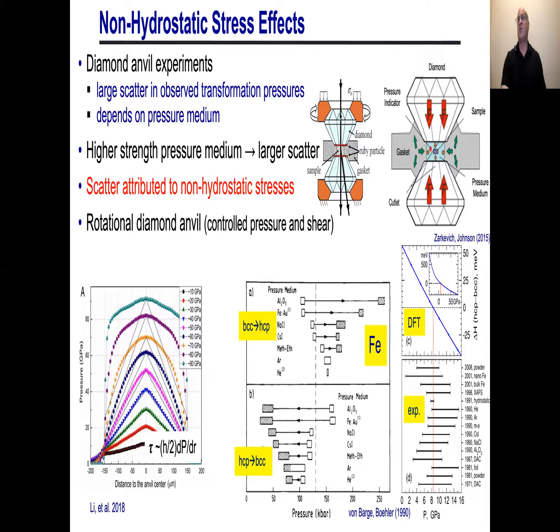People have also created what they call a rotational diamond anvil cell. So that's shown here. It's just like the original one, except you twist one diamond relative to the other about its axis. And if you do that, you can get a pressure distribution from the center of the diamond anvil cell that looks sort of like this. And if you have a pressure gradient, that implies that you have a shear stress. So what they're doing is controlling the shear by the twist that they apply. Okay, so that's an observation.